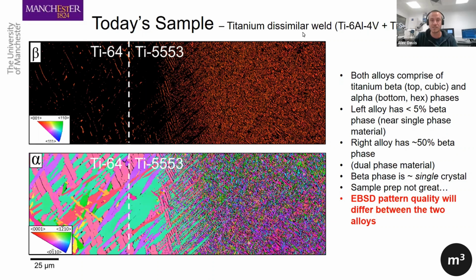Okay, so here is the EBSD setup again. And I'm about to flip over to Jack to show you this in the chamber. But this is a different view from what I showed before, because I want to point out 2 very key things here. So we have our sample tilted. This is our tilt angle here. Normally we tilt to 70 degrees, but this is not something you have to use. You can change that, and we'll get to that later.